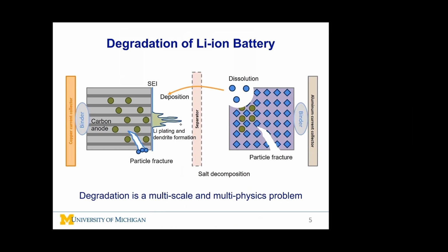For instance, the formation of solid electrolyte interface, or SEI, consumes cyclable lithium. Fractures in the anode and cathode cause increase of resistance and isolation of active material. Dissolution leads to the loss of active material. Lithium plating causes lithium deposit on the anode surface rather than integration into the anode for storage. These complicated processes and their interactions lead to capacity degradation.